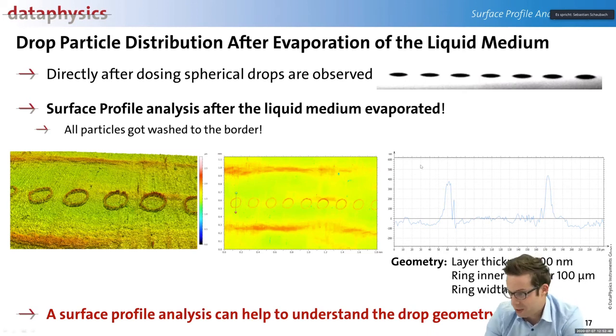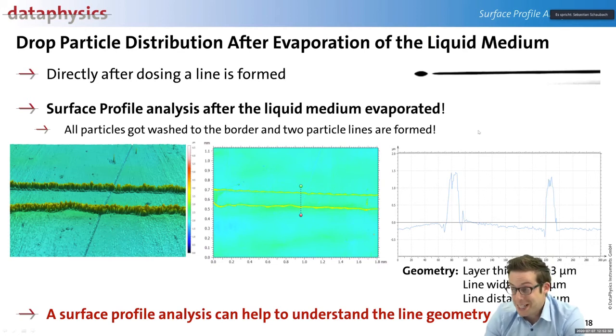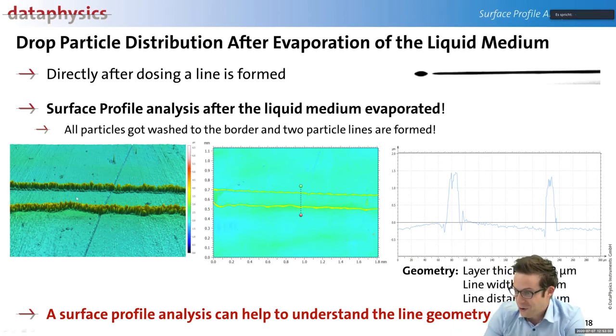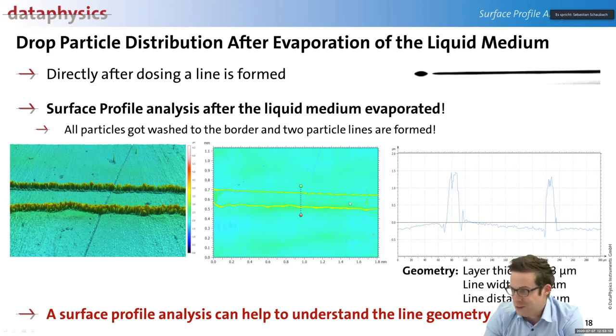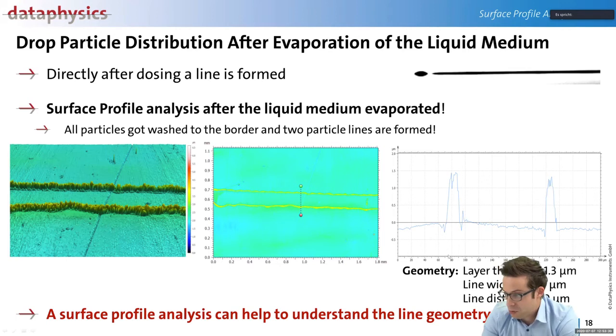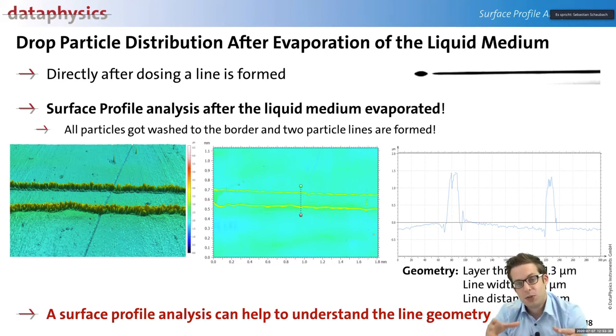Smaller drops are also very easily measurable. For the printed line: in liquid state it looked very nice, and under a bare eye or normal optical microscope it appears as a nice line. But in fact the particles migrate to the border when the liquid evaporates, generating two lines on the surface. The height here is around 1500 nanometers — much higher than the approximately 400 nanometers from the circular drops. The width of one of these lines is around 20 micrometers. With the surface profile analyzer we can get extremely detailed three-dimensional information on deposited inks on a surface.